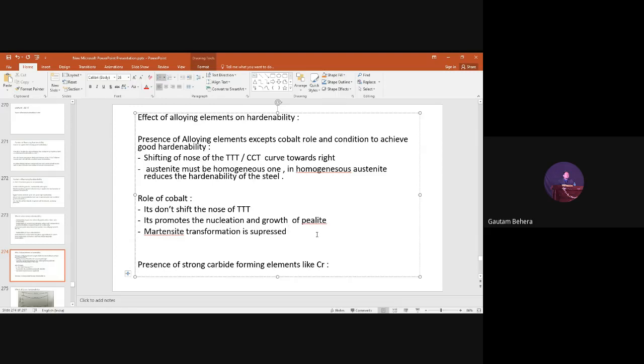That is one part. The second part is that cobalt also helps in the nucleation and growth of the pearlite phase, which is a diffusion-based transformation. So if diffusion-based transformation starts, martensite formation will not be easy, or it will be difficult, or it will be suppressed. This is the answer.